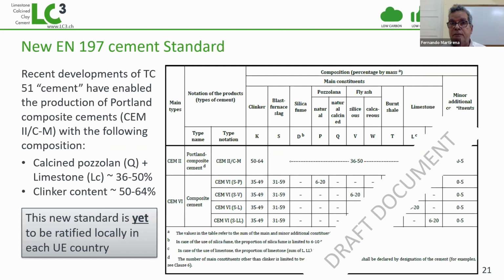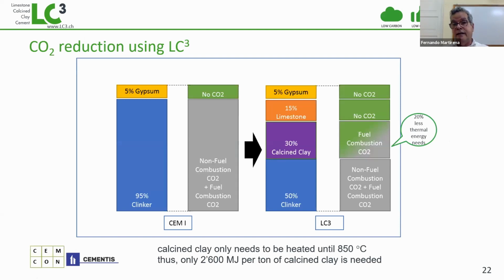And the good news, especially for African countries which follow, same as Cuba, the EN standards, is that the TC51 on cement, they have recently released a new standard, still to be ratified individually in each of the EU countries. But these standards, and you see it here, enable you to produce a CEM II, a Portland composite cement, with 50% clinker and a combination of up to 50% of other materials, including calcined clay and limestone. So LC3 is already present in its original composition in the European standards, and that's very good news.